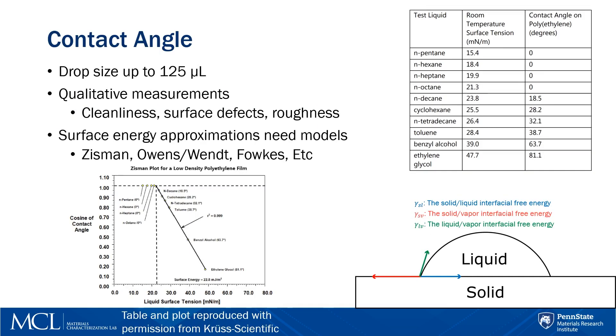So if we want to get an idea of the surface energy of a solid, it's going to take more work than just dropping a liquid onto a solid and taking a picture of it. What I just described could be very useful, however, for qualitative measurements, where typical contact angles are known for a certain liquid on a certain solid that has undergone polishing, etching, or some other treatment. For example, if you know the typical contact angle for water on plasma treated graphene, variations in the measured contact angle could help to identify when something has gone wrong in the synthesis or treatment steps.